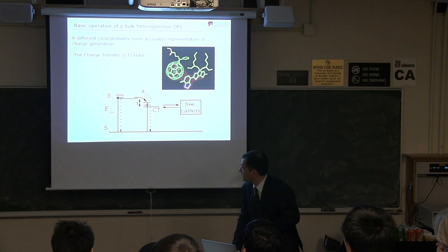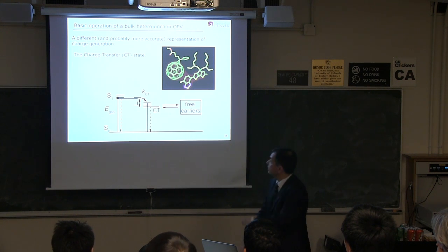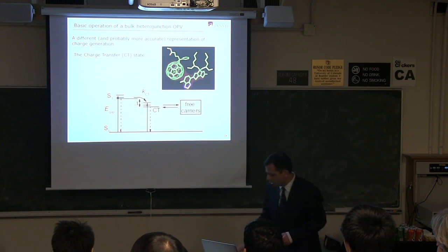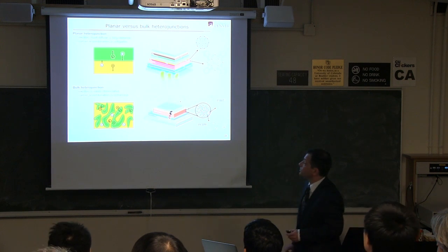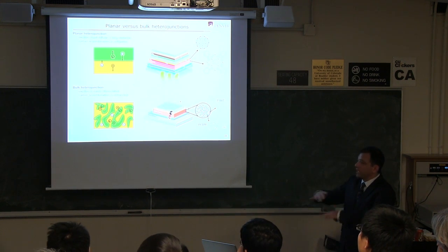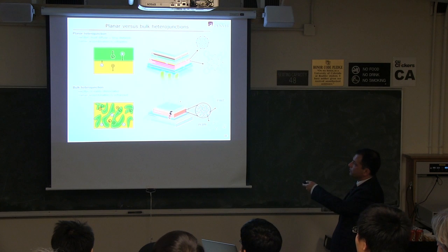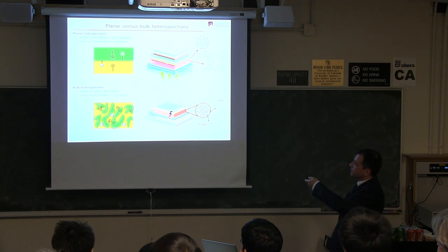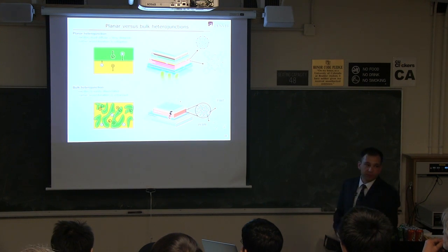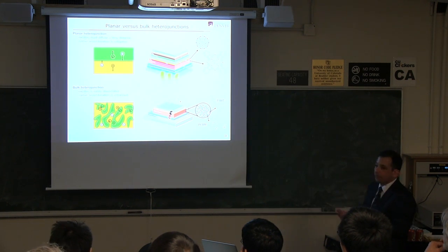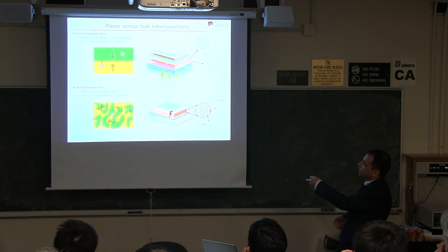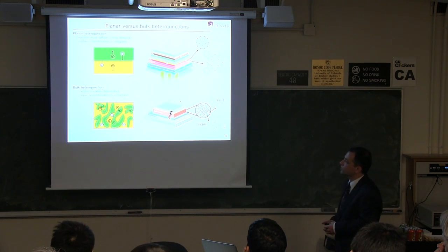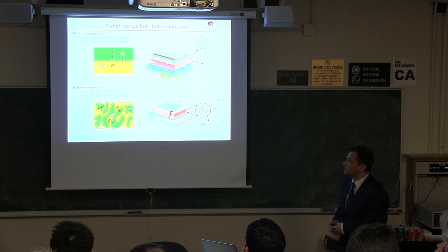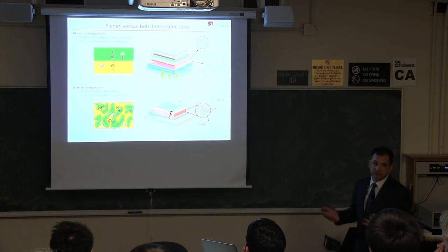Now, when we go to put these donors and acceptors, right, and this is the donor, this is the acceptor, put them into a device, we have two options. We can just make a planar heterojunction where we make a slab of the acceptor and a slab of the donor. And when the charges are separated, they're in a very well-defined medium through which they have to transport. That's nice because they can't recombine with each other except right at the interface, but otherwise they can get away from each other. The problem is that the exciton that is initially formed doesn't travel very far.